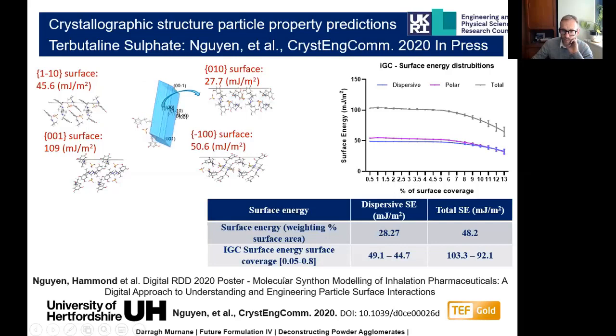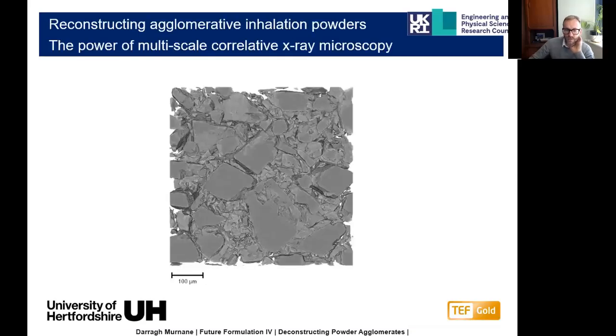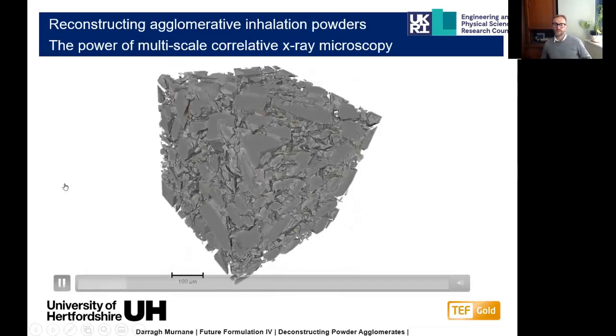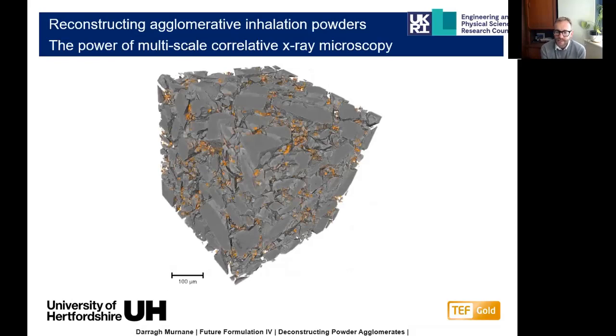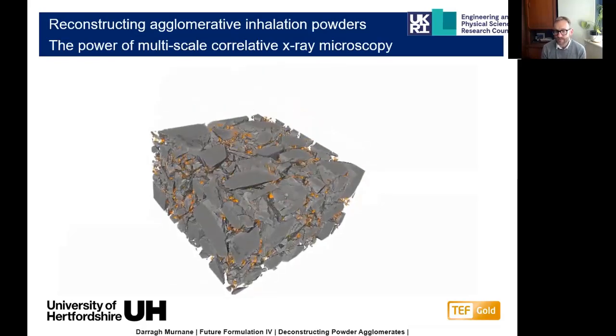So if we now start to reconstruct those powder blends, we can identify the individual large component of the products, the lactose monohydrate. We can identify how those drugs agglomerate. We can characterize the distributions of particle sizes within there. We can characterize where the drug distributes within the powder blends. I guess it's about reconstructing those powder agglomerates within a blend. So this shows an example of correlative microscopy. I think we've looked at this video in previous work, but what we're doing here is identifying where the fine particles are distributed throughout that blend.